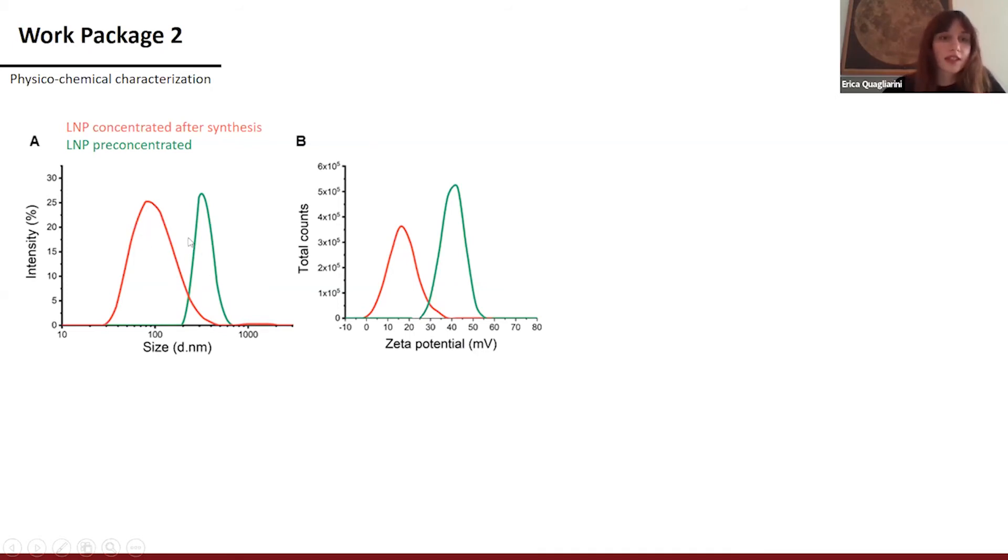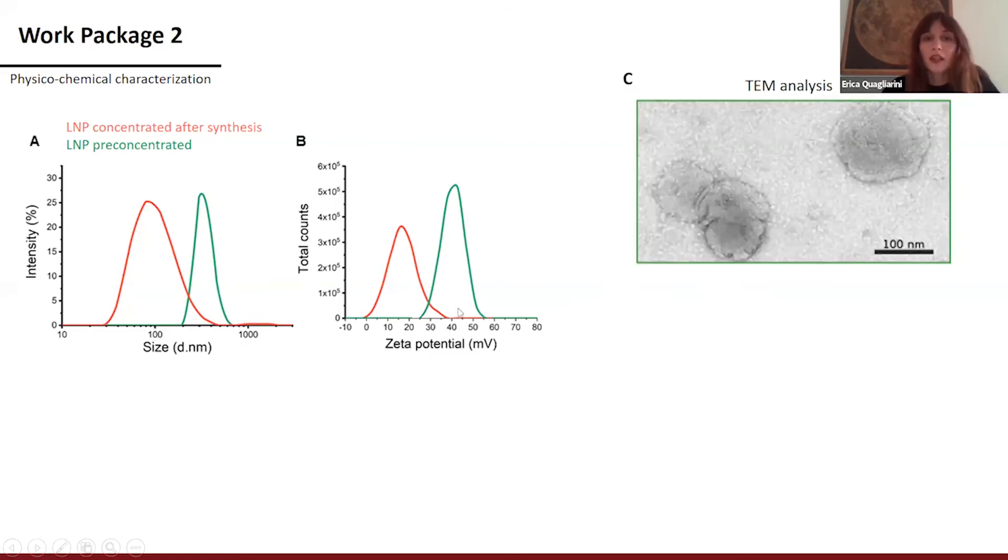This is probably due to greater steric hindrance in the microfluidic channel that can compromise the structural organization of these systems. For this reason, we decided to adopt the second approach, so the concentration after the synthesis process. That, as you can see, did not compromise the structural organization of the complexes. In fact, all the samples resulted small in size with a size of about 100 nanometers.